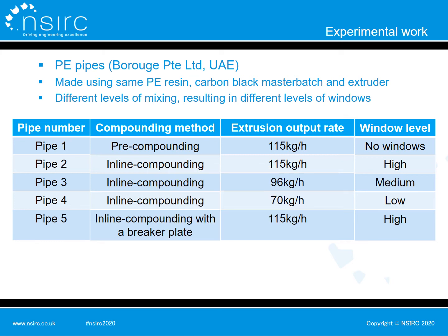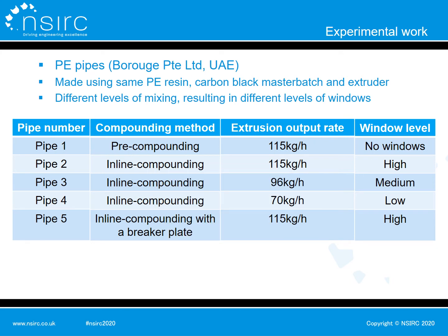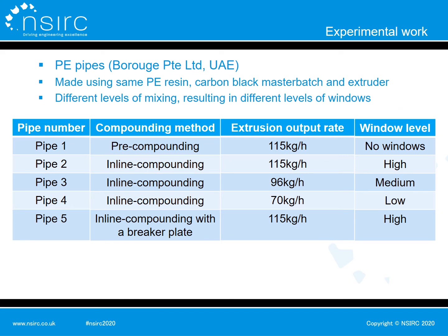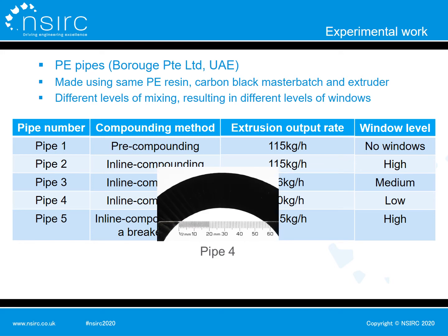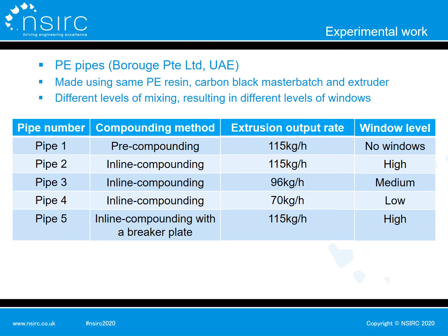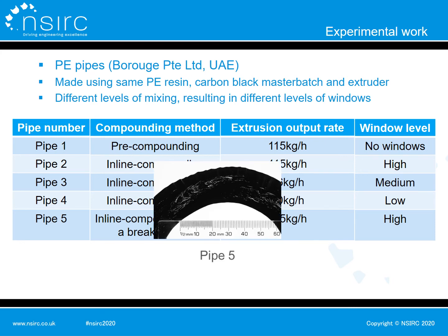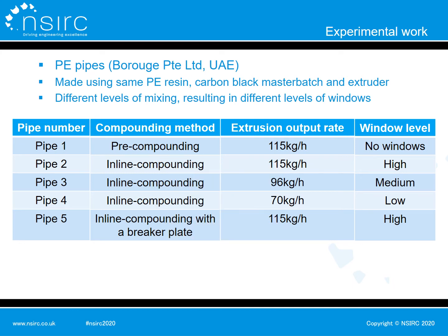Pipe 1 with no windows was extruded using pre-compounded material with the highest extrusion output rate. Pipe 2 with a high level of windows was inline extruded using the same extrusion output rate as pipe 1. Pipe 3 with a medium level of windows was inline extruded using an extrusion output rate lower than pipe 2. And pipe 4 with a low level of windows was inline extruded using the lowest extrusion output rate. Pipe 5 with a high level of windows was inline extruded using the same extrusion output rate as pipe 2 through a breaker plate.